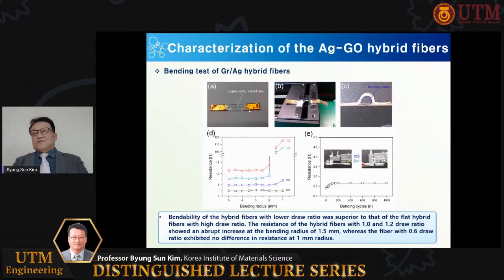In the characterization of the silver graphene hybrid fibers, the bending test of the hybrid fibers was carried out. Bendability of the hybrid fibers with low draw ratio was superior to that of the flat hybrid fibers with high draw ratio. The resistance of the hybrid fibers with 1 and 1.2 draw ratio showed an abrupt increase at the bending radius of 1.5 millimeters, whereas the fiber with 0.6 draw ratio exhibited no differences in resistance at 1 millimeter radius.